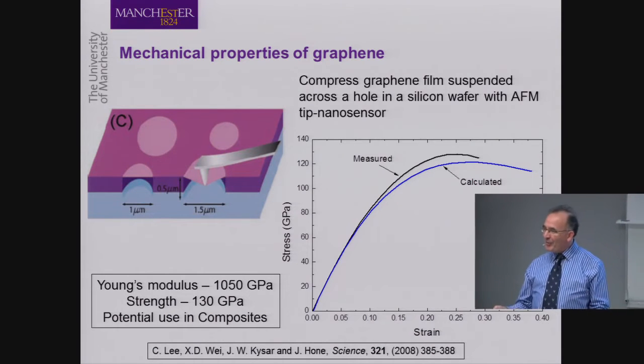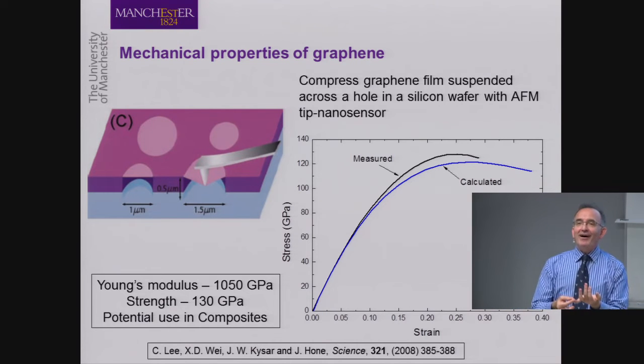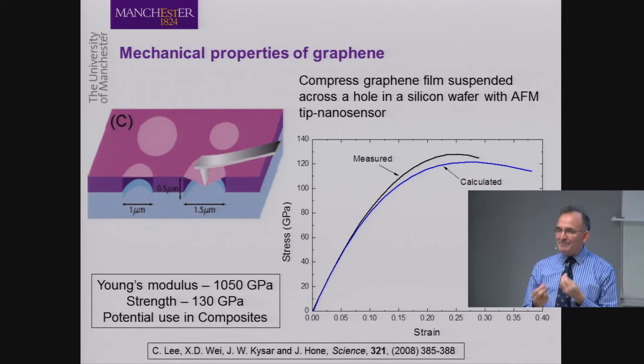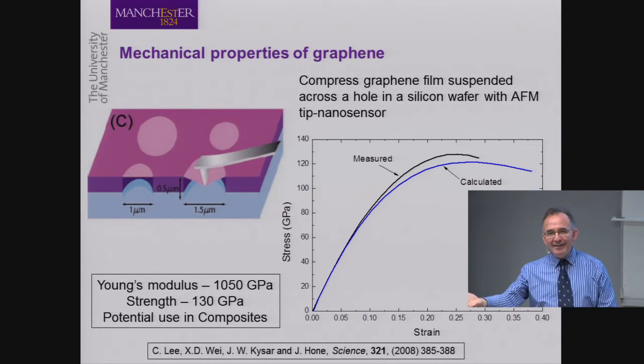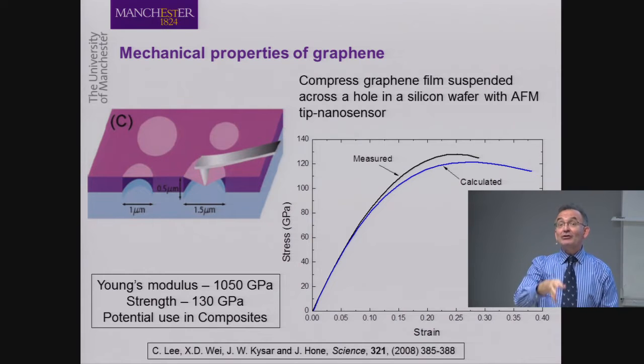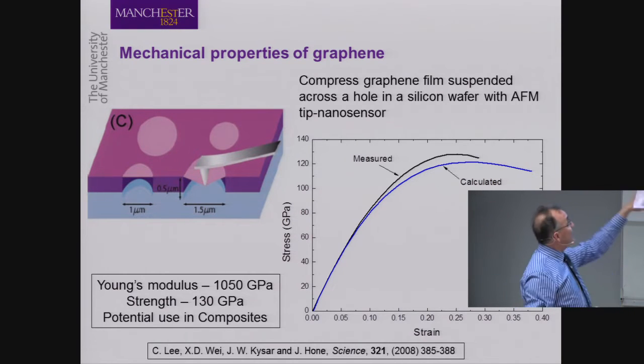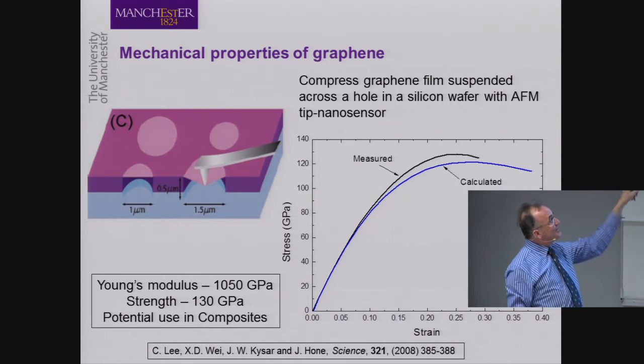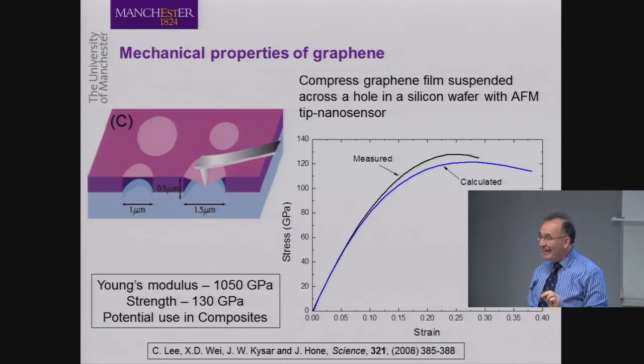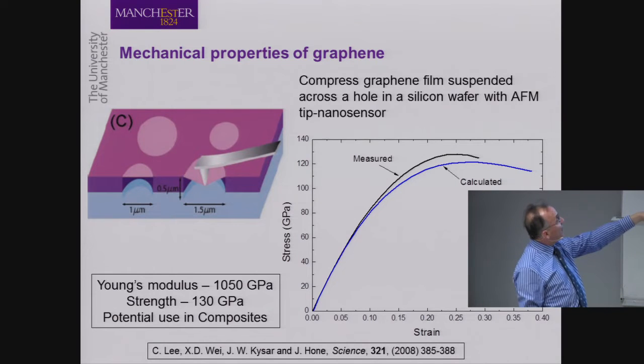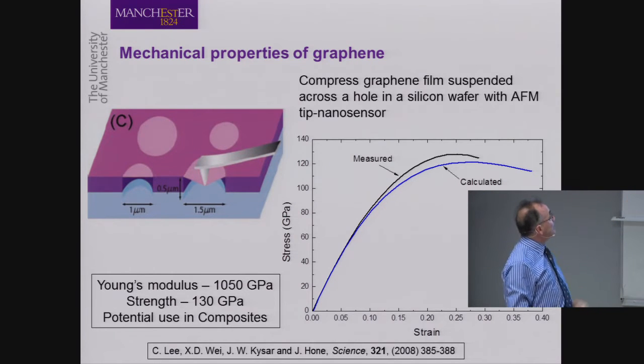How can we measure those properties? It's not easy. First of all, you need to have the graphene flake. And second of all, you need to develop the test methods and the measuring equipment, the strain gauges, to measure stress and strain in order to calculate stiffness and in order to capture the entire stress-strain response. And we can see here an example where you have a cantilever beam with an AFM tip nanosensor to measure the strain developed on that graphene flake. And from the stress-strain curve, we can see that we have the very high strength of 130 gigapascals and the Young's modulus of 1,050 gigapascals.